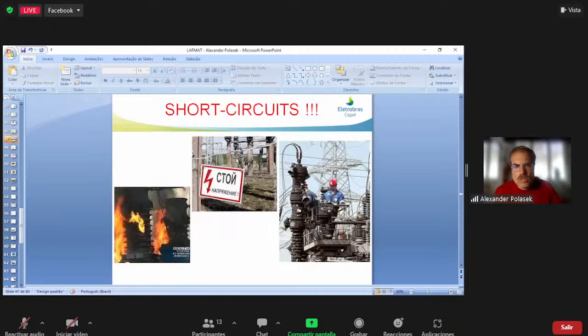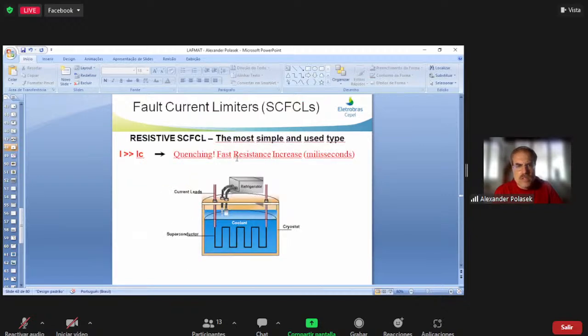Short circuits are also a big problem for the electrical grid, and sometimes the conventional protection devices are not able to prevent damage like that which you are seeing. And so fault current limiters are also a very promising application. Here I'm just showing you the most simple and most common one. There are also other kinds of fault current limiters. The idea is that if you have a superconductor in series with the line, in line with the grid, during the normal operation, the impedance is very low, it's negligible.